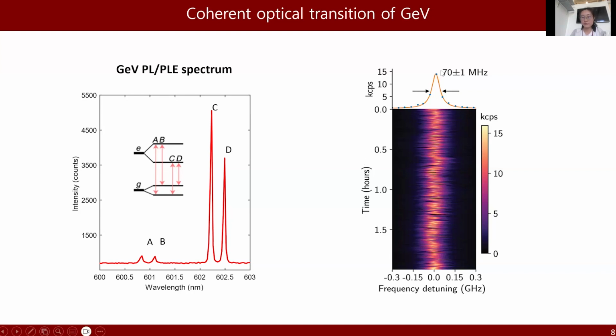In our specific case, we took the PLE scan at 4 Kelvin, and the linewidth we got for GeV is 70 megahertz, and this number is very close to the transform-limited value. So in other words, the GeV is a very good candidate for an atomic antenna.